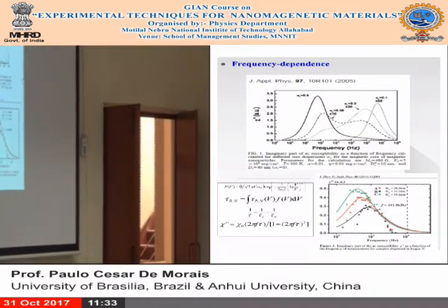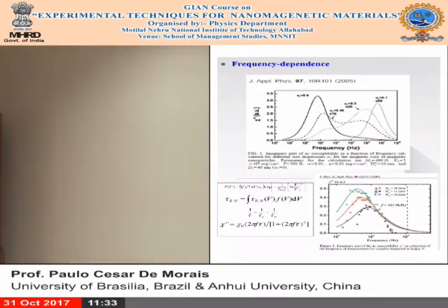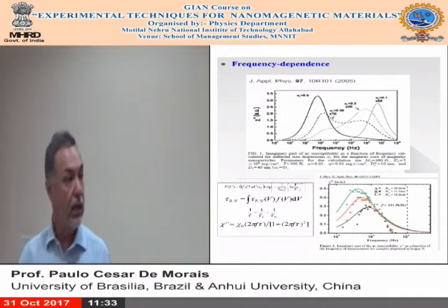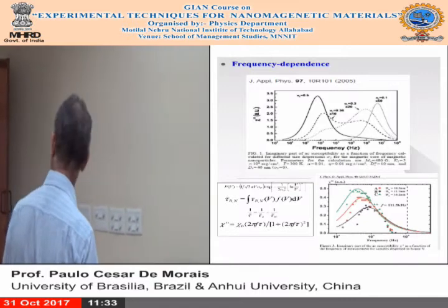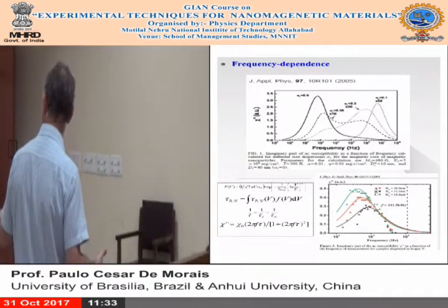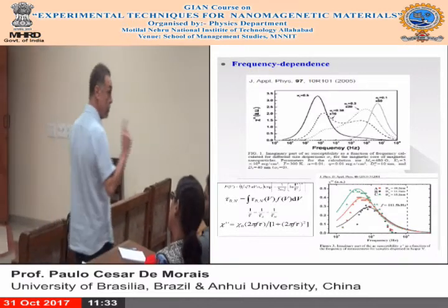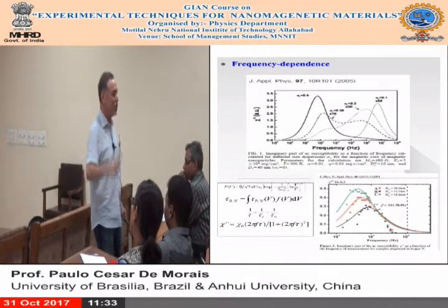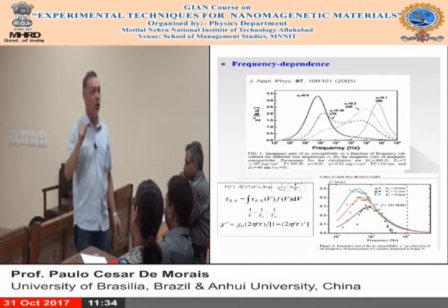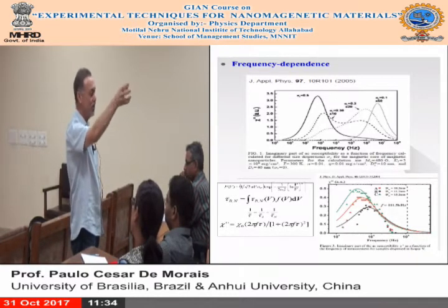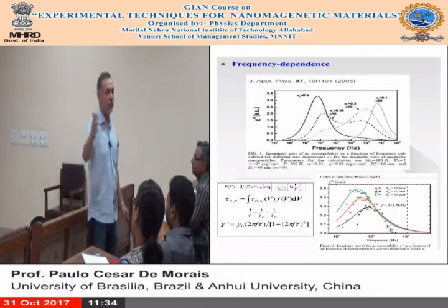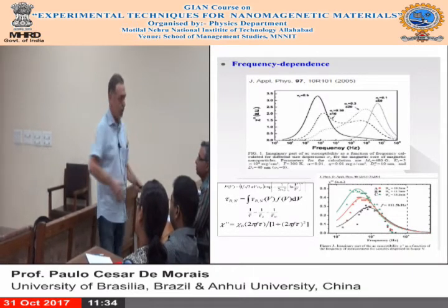PVA. Also, there are many systems you can play with, of course. It doesn't mean it needs to be only two phases, could be more. But you can mix liquids with different viscosity, and then you can play between a system which is dominated by Brownian relaxation up to Neel relaxation. And also, you can cool down your sample a little bit, and then the viscosity goes very high. It goes to a point where the particle cannot turn around anymore. And then you can check how important the Neel relaxation time is.